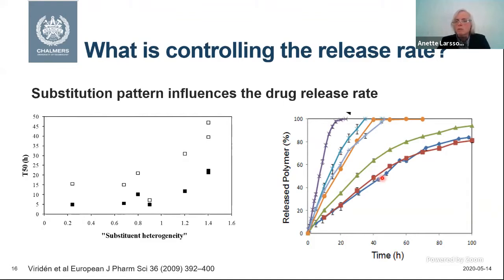So here, for example, the T50 value is around 45, corresponding to these points. And you can see that the slow ones here have the highest degree of heterogeneity in the substitution pattern, meaning that the most glucose units were cleaved away. And if you want, you can see this publication here for more information.